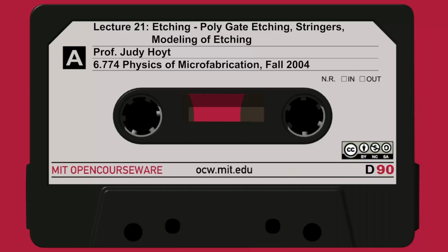The TiN is next, a very thin layer. That is your gate material. They then have tungsten that they fill it up with. So they have tungsten material, which is a little bit more environmentally friendly, or it's an easier material to work with to fill up the plug. So that's an example where the poly was completely removed. So new types of things have to be done with forming gates these days.